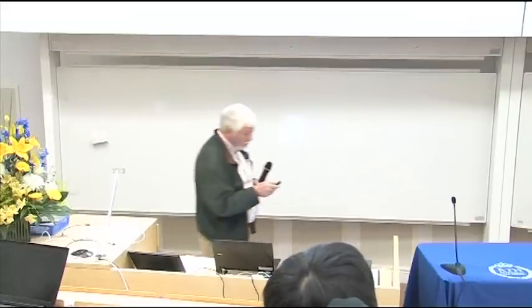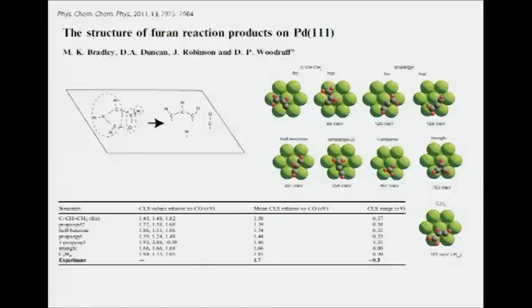And so finally, I just want to show one result from our own work recently, where I have a student who's been doing some DFT. We've been doing some detailed structural work of this furan decomposition on palladium-111, where the conventional wisdom is that you certainly see a co-adsorbed CO and that you produce a C3H3 species. And we've been trying to figure out what on earth this C3H3 species is.